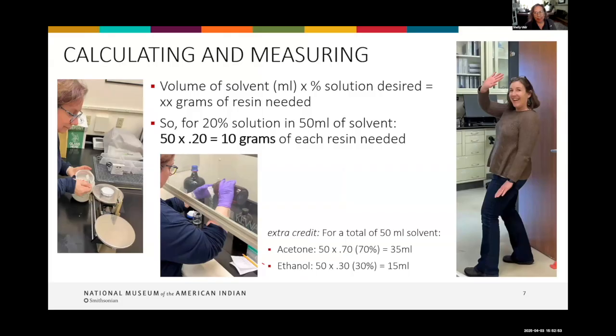The calculating and measuring can seem challenging if you haven't done it before, so let's walk through that. First of all, you decide how much you want to mix. In our case, we were mixing 50 milliliters in each jar. Second, you decide the percentage of resin that you want to add. Lower solutions like 5 or 10% are often used in conservation for coatings or consolidants. This can help control ultimate sheen and surface darkening for their work. The idea is that it's better to apply thin than thick because you can always add, but you can't easily take it off.